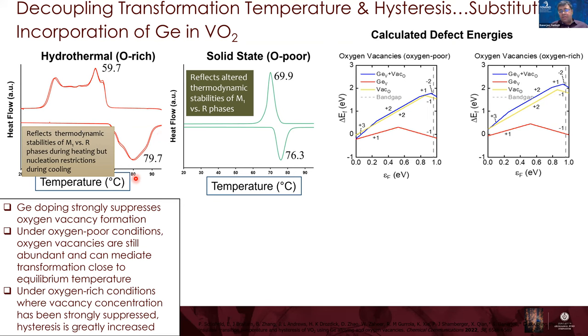The high temp, the heating transformation is not so affected by anything because it's nucleated at phase boundaries and twin faults, but the cooling transformation is extremely sensitive to the oxygen vacancy concentration. So by tuning the alloying element and the oxygen vacancy concentration, we can disentangle the hysteresis of the transformation from the transformation temperature.